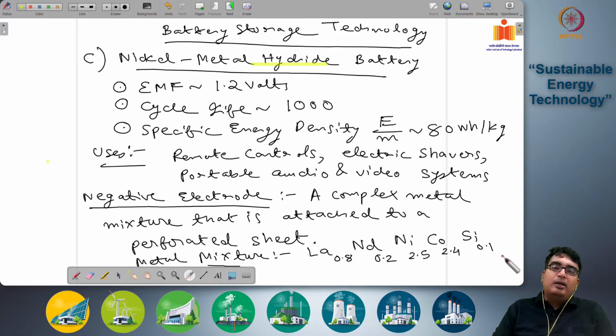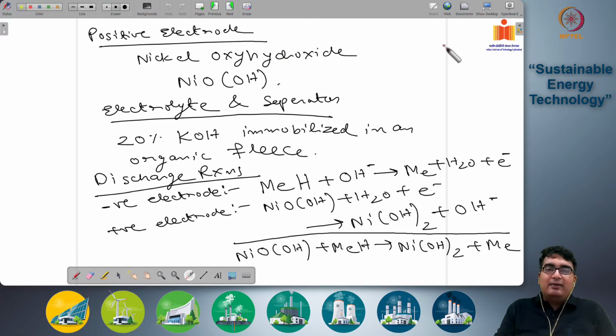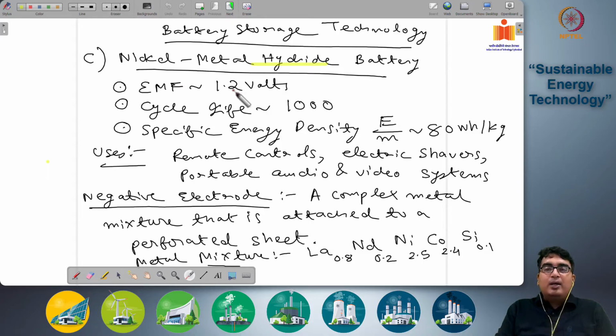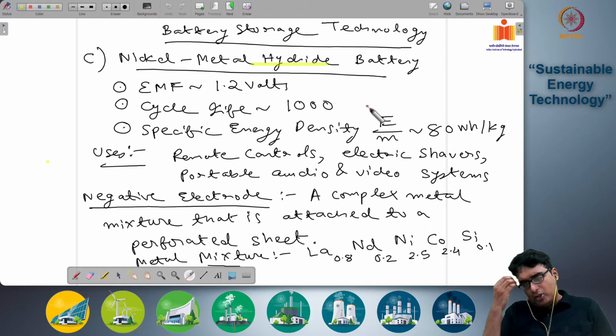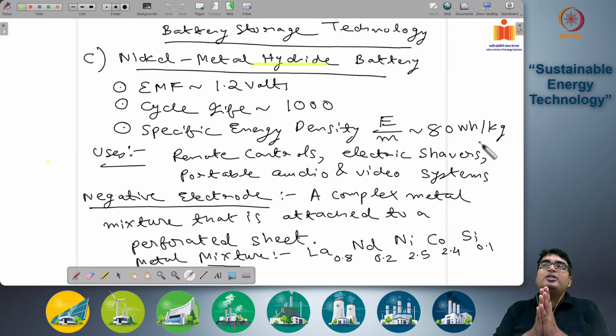On the positive electrode side, we still have the nickel oxyhydroxide material that was used for the nickel cadmium based battery. Here we are also getting an EMF of around 1.2 volts, but a much higher cycle life of 1000 cycles. If you remember, the nickel cadmium battery lasted only 200 to 300 cycles. This one lasts around 1000 cycles, and the specific energy density is around 80 watt hour per kg. So it has a reasonably good energy density as well.